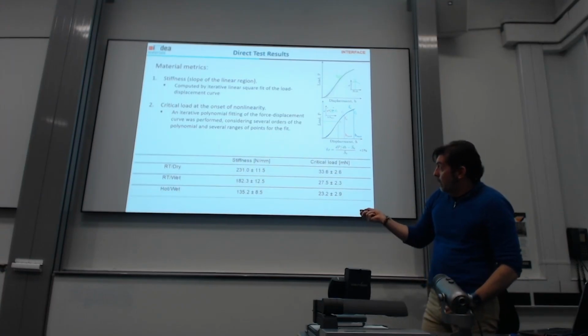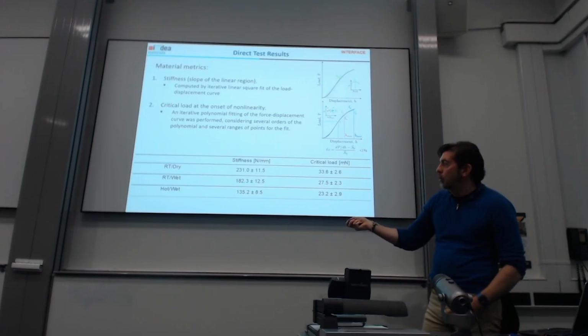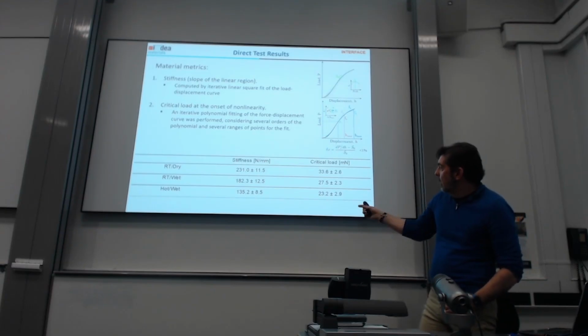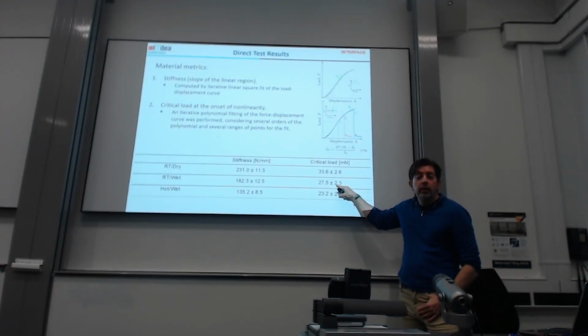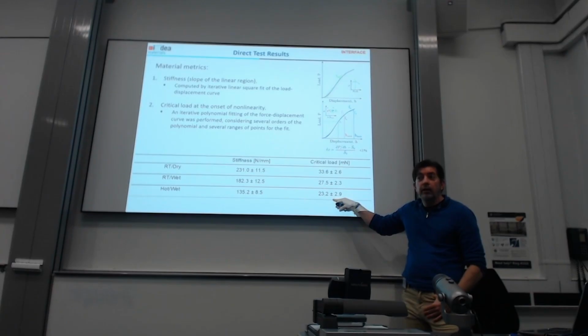And this is what you get. We get the stiffness and the critical load for the three conditions. We look at the dry condition, wet, and hot wet. We have the stiffness and the critical load. You can see it decreases for the wet condition and more for the high temperature condition.